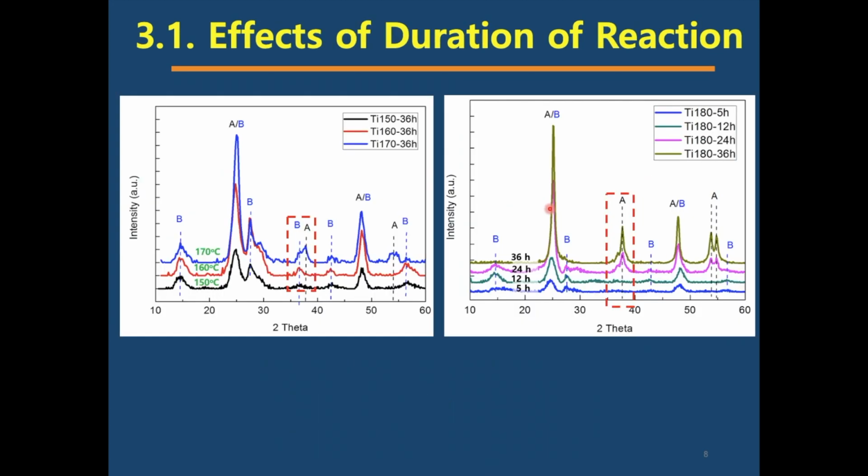So next, we study the effect of duration of reaction. Whether at longer reaction time, is there any change of the crystal structure? Well, at low temperatures, 150 to 170, almost no change, even though we increase the reaction time to 36 hours.